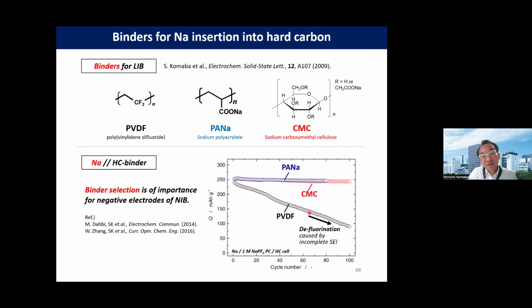The capacity degradation for only PVDF is due to defluorination caused by incomplete SEI formation on the surface of hard carbon. In the case of fluorine-free binders, as you can see here, it is quite effective to improve the cycle performance of the hard carbon electrode. Because of the binder success, we can stabilize the electrochemical sodium insertion and extraction. Then we can open a new field for sodium insertion mechanism study.